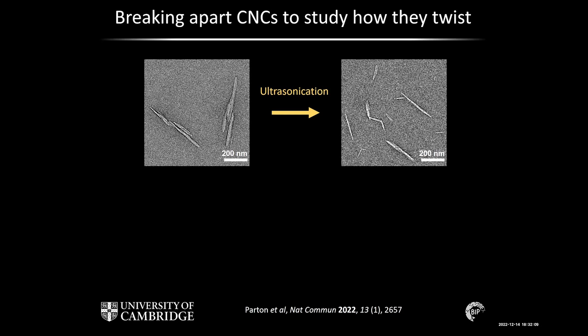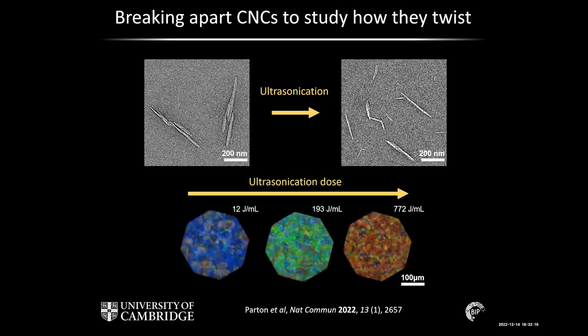And what we find, interestingly, is that when we then use that to make one of these colorful films, we get a red shift in the color of the final film. So as we increase the amount of ultrasonication, we go from a blue film to a green to a red, as you can see here in the microscopy images. Essentially what's happening is that this helicoidal structure has a larger periodicity, which means it's twisting less. As a consequence, it reflects a longer wavelength of light, and that causes the apparent color to go from blue to green to red. And eventually it will reflect in the infrared and we won't see any visible coloration at all. So this suggests that when you apply this ultrasound and change the shape and size of the CNCs, you change how strongly they interact in this chiral, twisted fashion.